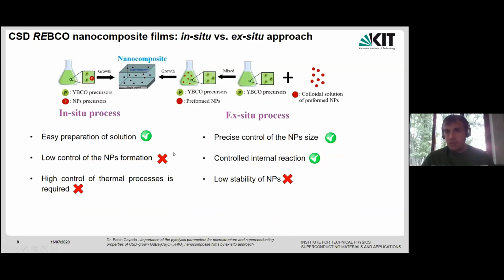But not only this, when we use CSD and we want to prepare the nanocomposites, we also have two options. First is the so-called in situ process. This has been used since the beginning of the CSD. This was the so-called conventional approach. In this case, we prepare the solution with the YBCO or REBCO precursors, and we also add the nanoparticle precursors. In this case, the nanoparticles are created spontaneously during the growth of the process. So they don't exist in the solution, but they are created spontaneously during the growth.